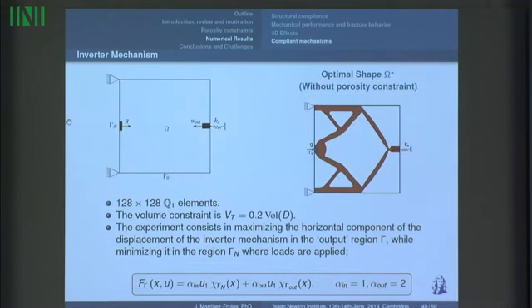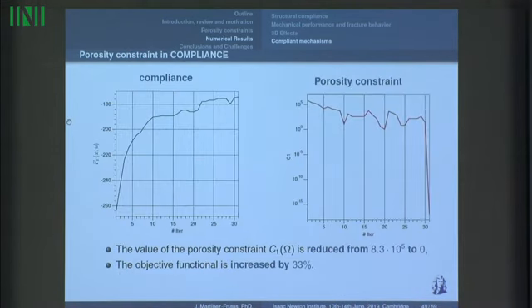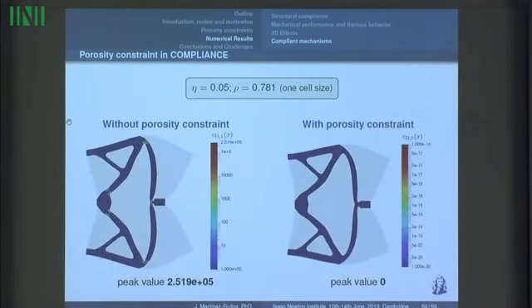So the optimal shape that we obtain without imposing this porosity constraint is this one. And if we impose a porosity constraint in compliance, we see that we have a reduction to 0 of the constraint, but at the cost of increasing this functional by 33%. So this is something that we could expect, because we are trying to maximize a functional related with the flexibility of the mechanism, but introduce a porosity constraint in the compliance, which has to do with the stiffness. So we have something like a multi-criteria problem that, of course, this multi-objective problem, we can control it by modifying the parameter eta. This parameter eta in porosity.